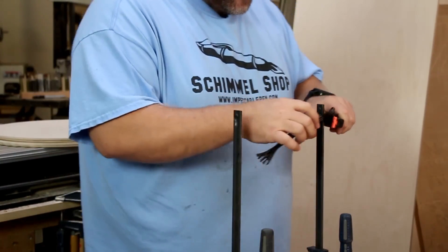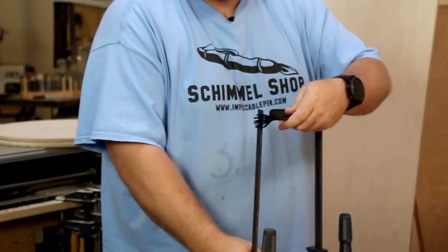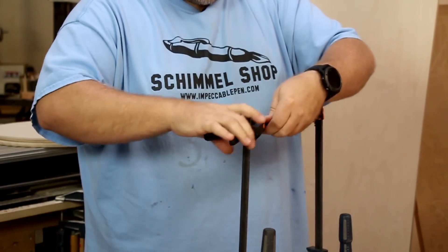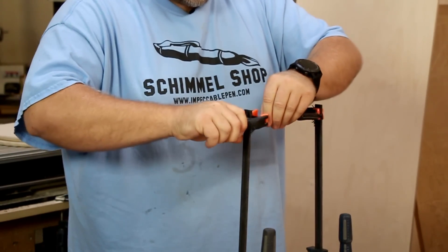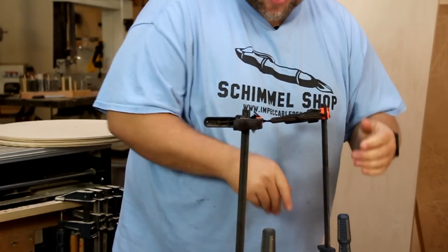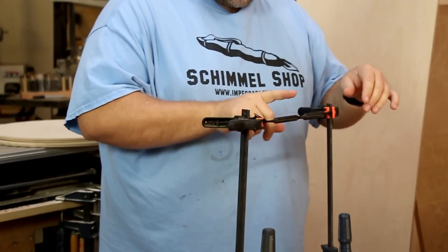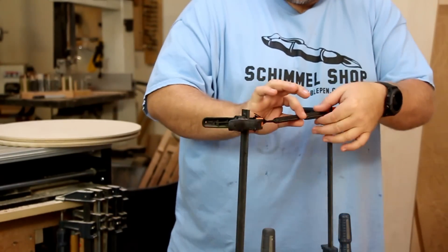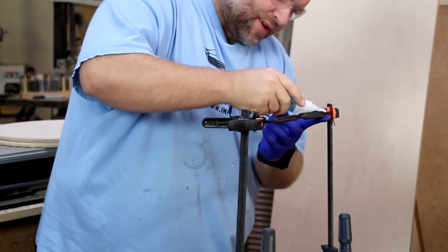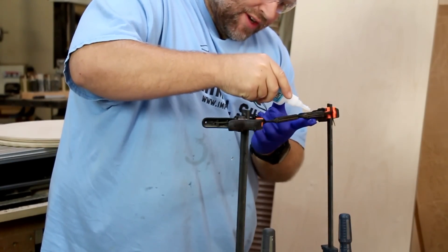When I go to put it on the clamps for gluing, I'll simply put one end in and get a good clamp on it, then move the other clamp to where I need it. A lot of times I'll twist the carbon fiber once or twice to make sure I've got a good tight fit, then pull the clamp out and tighten it down to my bench. I've got a pretty good taut line — not crazy tight, but tight enough that the carbon fiber is pulled flat on the tube. Then I'll take my thin CA and just pour it on here. The thin really spills over nicely, and I want to really saturate the carbon fiber all the way to the bottom. I'll use my finger to smooth it out down there.